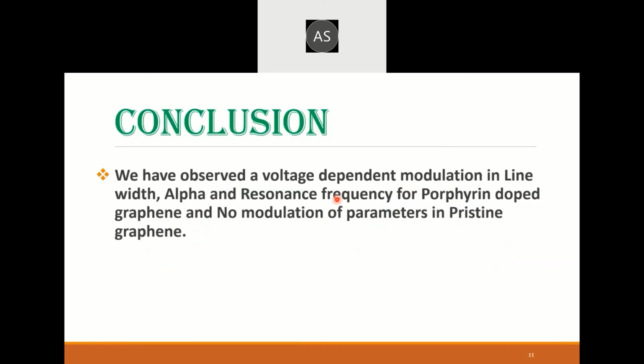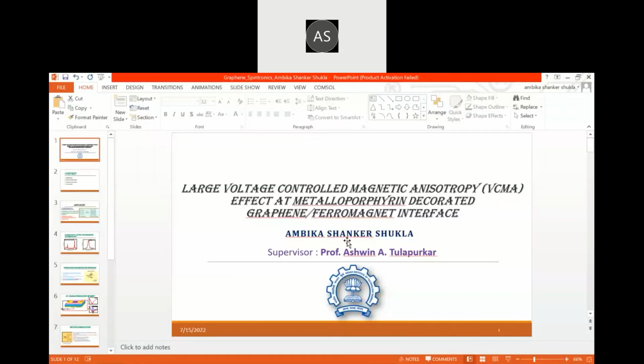So I'll conclude with this quickly: we actually see this kind of modulation only for porphyrin doped graphene, and no modulation of parameters has been obtained for the pristine graphene. So there is no modulation for pristine graphene, whereas if you dope your pristine graphene with a porphyrin, your platinum doped porphyrin, you will see these kinds of modulation. So thank you very much for your time. It's very quick, and if you have any questions, I'll be happy to answer them.